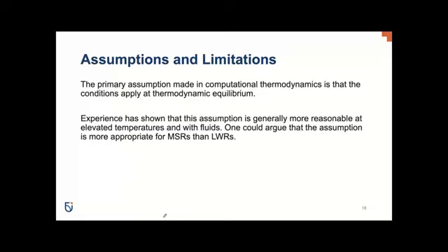So experience in the field of computational thermodynamics applied to nuclear fuels has shown that the assumption is generally more reasonable and more appropriate at elevated temperatures and also with fluids rather than solids. That's not to say that the assumption is invalid for solid materials. It's just to say that it is a better approximation for fluids, both gases and liquids.